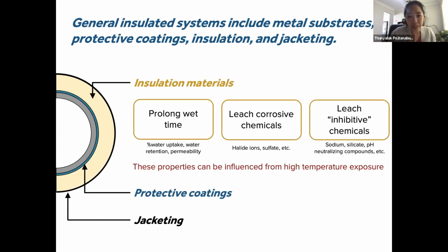And we know that the insulation materials can affect the CUI in different ways. The first one is that due to different properties in terms of the water retention, it can prolong the wet time. It can create an enclosed environment where water can be trapped and corrosion can proceed undetected. It can also leach corrosive chemicals such as chloride, fluoride, or sulfate. It can also leach inhibitive chemicals, and these include silicate, for example, or some pH neutralizing compound that increases the pH of the water when it enters the insulation.